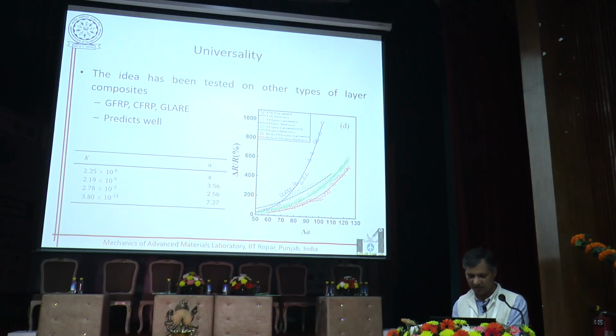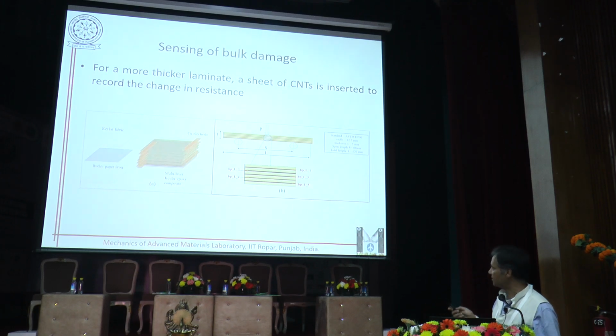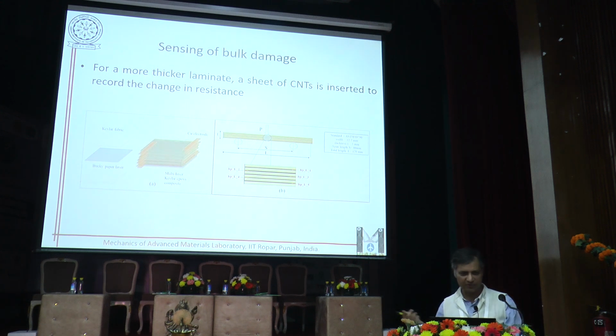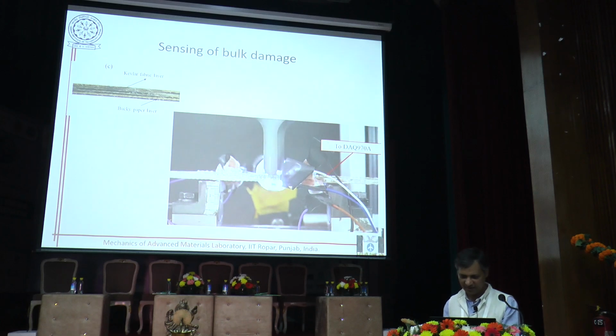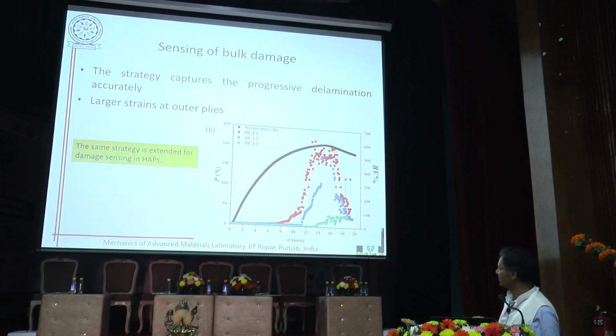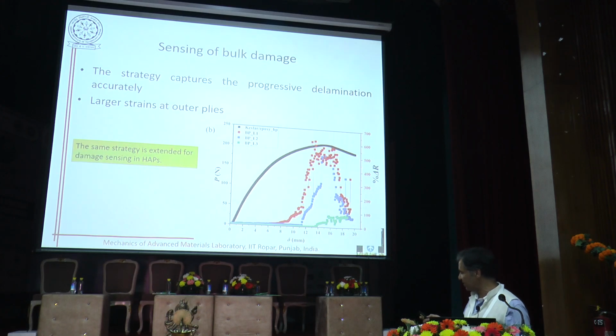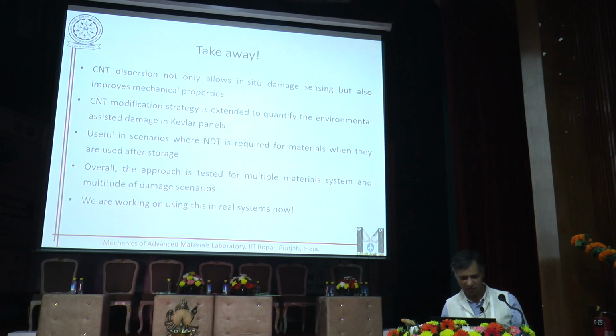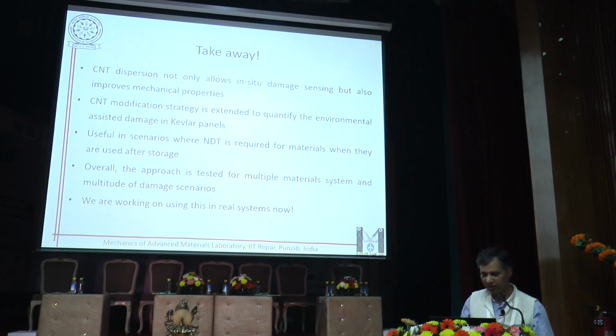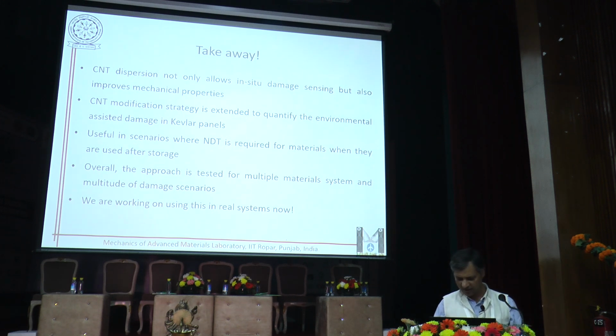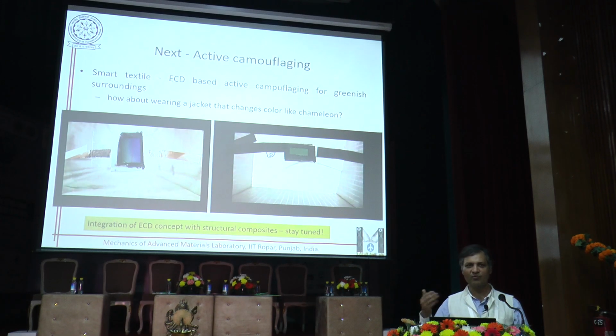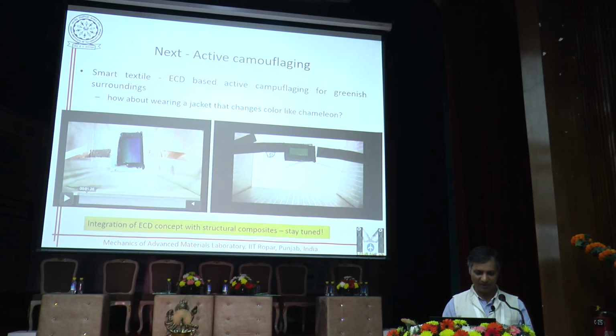Again, we used a similar technique to detect delamination in the bulk system. We put bucky paper sheets, which are basically sheets of CNTs, between the laminas, and verified the same thing here. You can see that if you put them at different layers, you can monitor the progressive damage in the composite, because each signal comes after a certain time. So we can see how the damage grows inside the system. To conclude, the takeaway is that CNT dispersion allows you to monitor damage in the system. It also helps in improving the mechanical properties. Now we are looking to scale it up for some real applications. I just quickly want to show this. The next step is that we are trying to make a textile which is more smart, just like a chameleon.